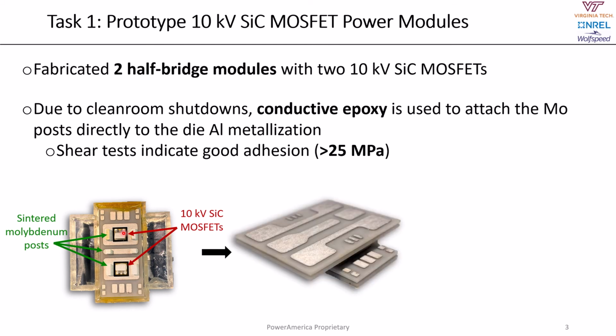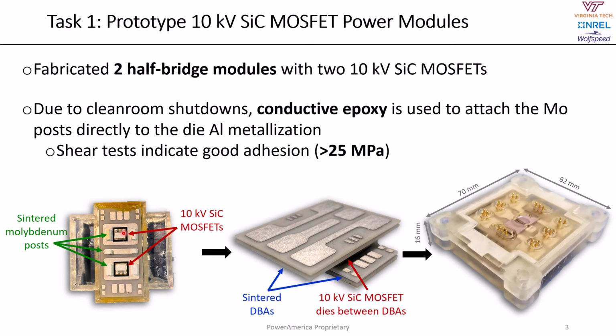So once this bottom half is completed, once the molybdenum posts are attached, we then attach the top DBA substrate, and so the silicon carbide MOSFET is sandwiched between these two direct bonded aluminum substrates, shown here. This is one of the 10 kV prototypes, fully assembled, where it's got spring terminals for the interconnect, 3D printed housing, which allows us to develop a unique lid geometry for relieving the electric field outside the power module, and silicone gel encapsulant.